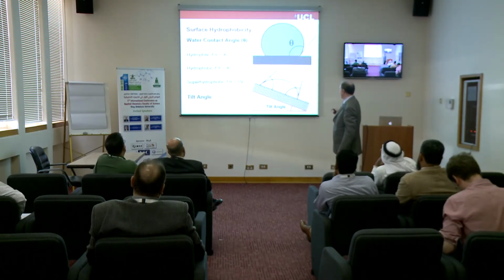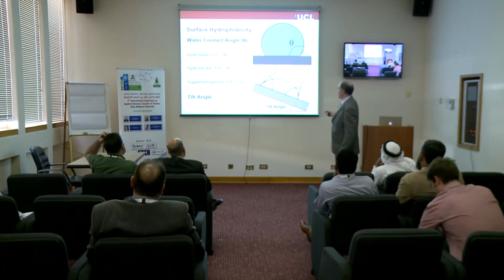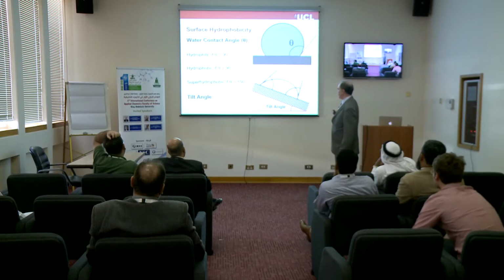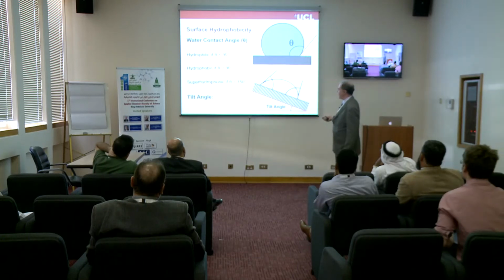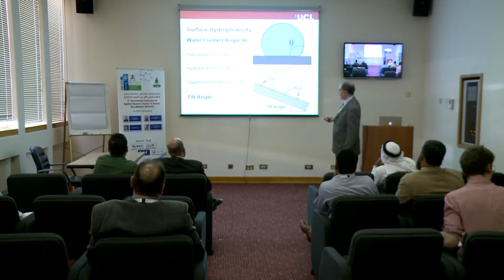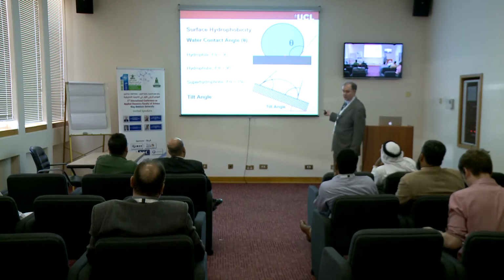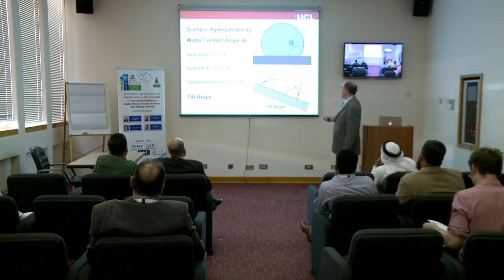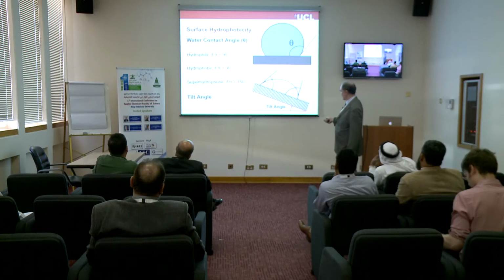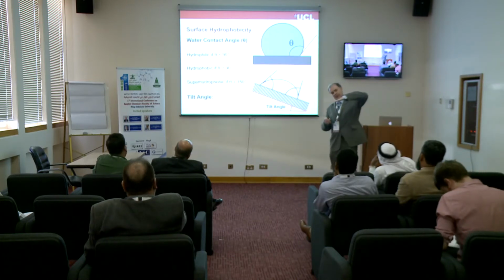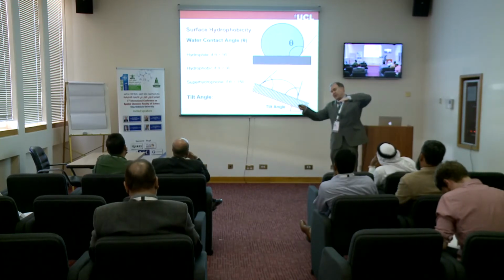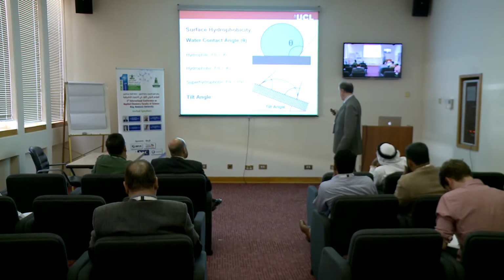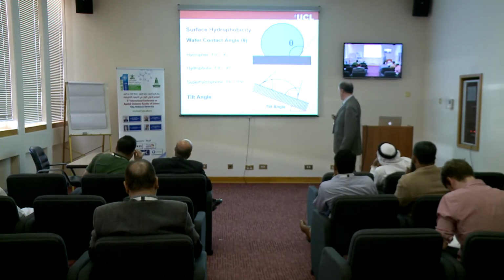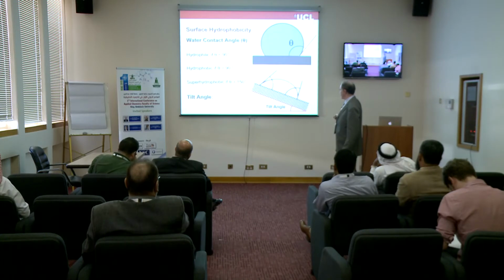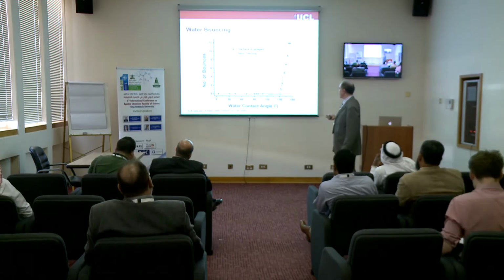And so we've looked at this and we've made a series of surfaces where we induce a surface roughness and a low energy surface. To be super hydrophobic, you need a contact angle here greater than 150 degrees. Also, things which are important are the tilt angle. That's the angle which you need to tilt the film up before the water droplet starts to move across the film. And there's also 2 other terms which are the advancing and receding contact angles. That's the advancing and that's the receding one.